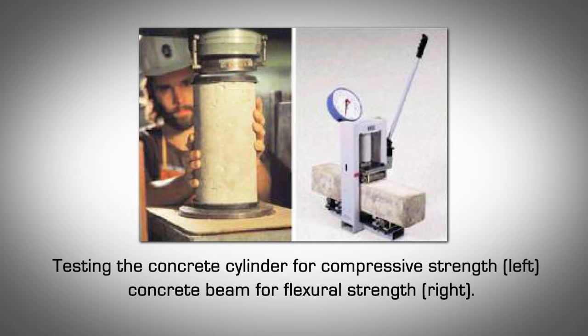A 12-inch high by 6-inch wide cylinder of concrete is cast and cured for the appropriate time, usually 28 days. It is then compressed between two parallel faces. The stress at failure is taken to be the compressive strength of the concrete. It is generally expressed in pounds per square inch or megapascals at an age of 28 days. Concrete mix strengths used in ICF will most likely range between 2500 and 4000 PSI.